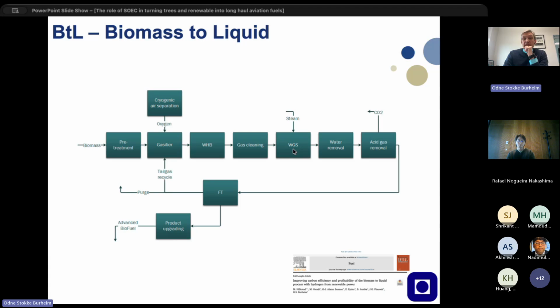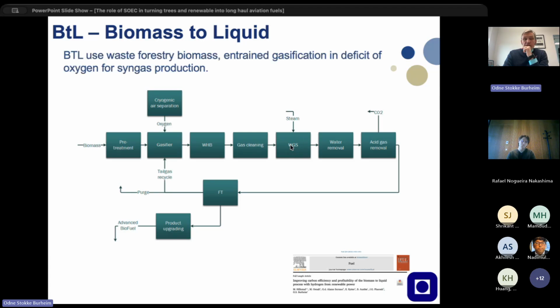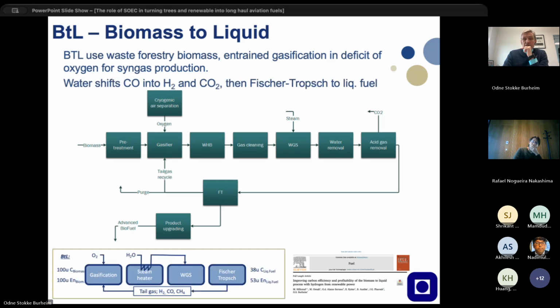And then, by adding more steam, we shift carbon monoxide into hydrogen and CO2. Because when we add steam, we also tie up more of the carbon that could potentially have been fuel as CO2, so the carbon usage or utilization is kind of low.